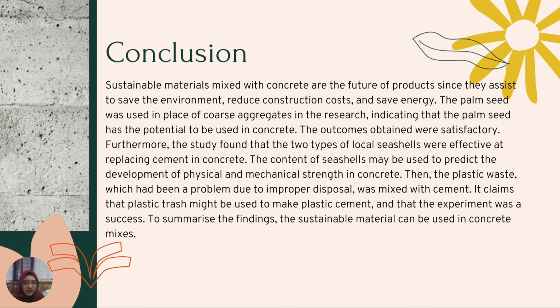Furthermore, the study found that the two types of local seashells were effective at replacing cement in concrete. The content of seashells may be used to predict the development of physical and mechanical strength in concrete. Then, the plastic waste, which had been a problem due to improper disposal, was mixed with cement. It claims that plastic trash might be used to make plastic cement and that the experiment was a success. To summarize the findings, sustainable material can be used in concrete mixes.